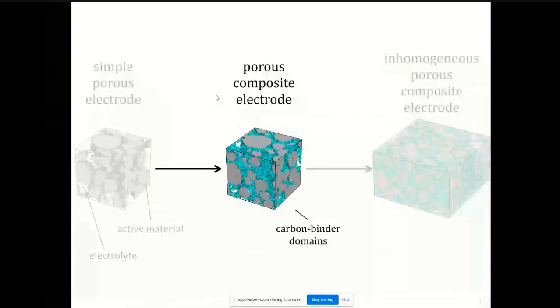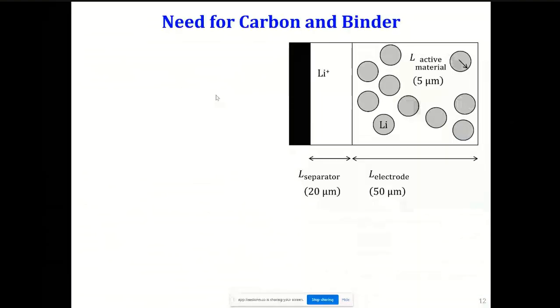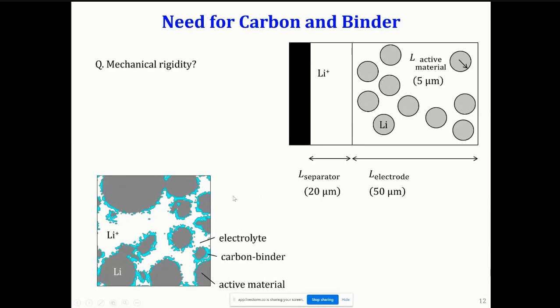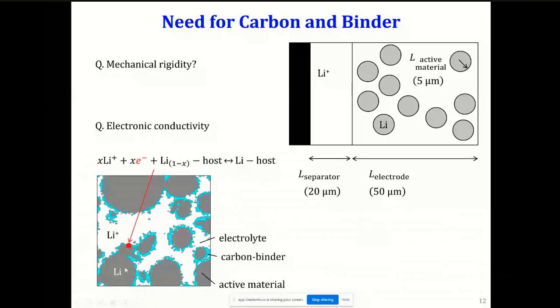Let's talk about the composite electrode part of it, right? One thing I haven't told you about is that this simple configuration has limitations. First is, how are you going to ensure the mechanical rigidity? To ensure mechanical rigidity, you would need to put in something like a polymeric phase, which is traditionally called binder. Another issue is most of the electrode materials, especially on the positive electrode side, are poor conductors of electrons. And when these intercalation reactions take place at the interface of electrolyte, which is the white phase, and the active material, which is the gray phase, they need electrons. And those electrons are often supplied through the adjoining phase, which is carbon. So we need to put in both these phases to facilitate conduction as well as mechanical rigidity.